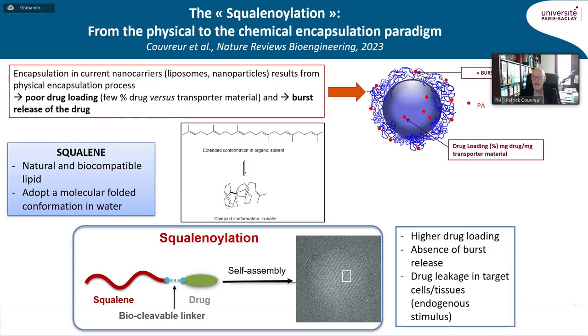But in general, when you are encapsulating a drug in current nanocarriers, including liposomes or nanoparticles, you are using physical encapsulation processes. This means encapsulation, entrapment, absorption, etc. And this results, as you can see here, in a very poor drug loading. Only a few percent of the drug compared to the amount of the transporter material. And the second limitation is that after administration of the nanomedicine, you will have an uncontrolled burst release of the drug, which is due to this fraction of the drug, as you can see here, which is rather adsorbed at the surface of the nanomedicine than really encapsulated into its core.